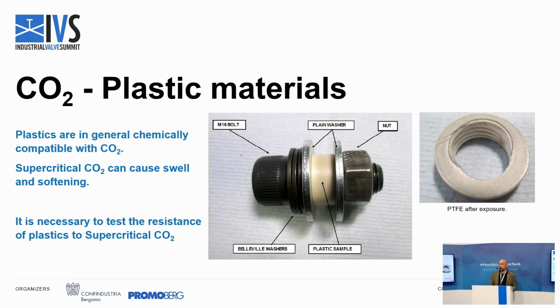Another problem is that there's no qualification process or certification. There's no standard for 100% CO2 in the supercritical state for plastic materials. We can test the valve with plastic seals in the valve, but there's no qualification process for the plastic materials. So we started to run testing on different plastic materials with this kind of configuration, which basically recreates the axial force that a plastic seat on a ball valve can be required to withstand.